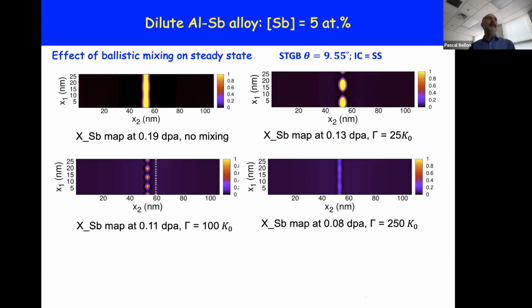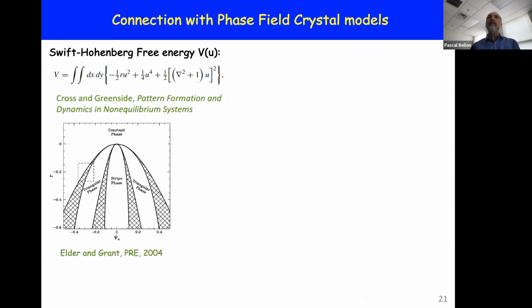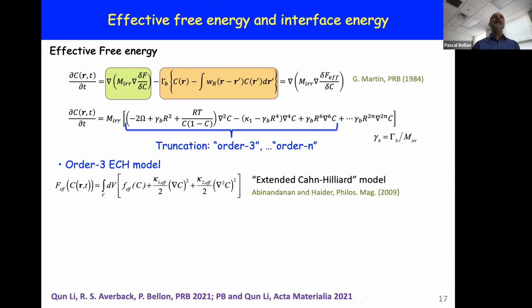There is one approach that may provide a partial answer to your question. I mentioned that Georges Martin introduced this effective free energy for capturing the evolution of these dynamical systems with competing dynamics. If you look at the first term here, if I absorb this gamma B into omega, it's as if I had an effective thermodynamic model with an effective heat of mixing, or you could just keep the heat of mixing the way it is at an effective temperature.